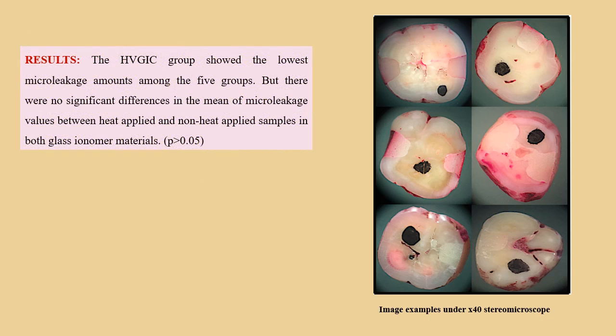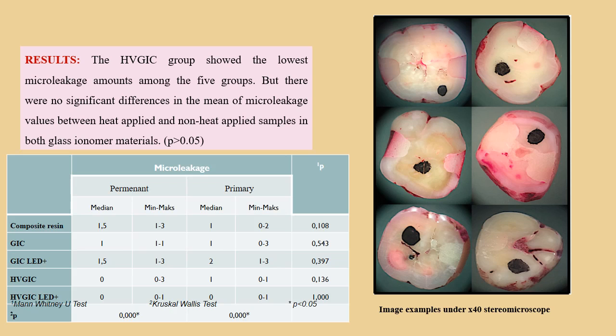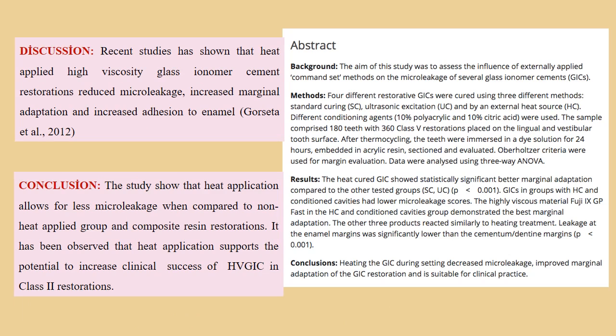The high-viscosity glass ionomer group showed the lowest microleakage amounts among the 5 groups, but there were no significant differences in the mean of microleakage values between heat-applied and non-heat-applied samples in both glass ionomer materials.